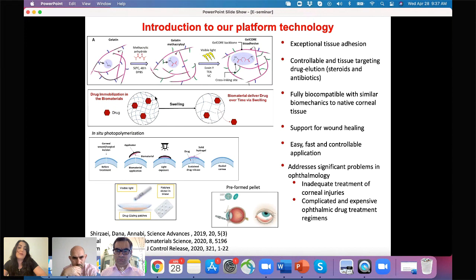And once we form these nanoparticles, they can be combined with the bioadhesive pre-polymer solution. And then the solution can be applied on the defect site on the cornea by using an applicator. We can use a contact lens as an applicator. Once we place the contact lens on the surface of the eye, we photopolymerize the hydrogel, and after that, the contact lens can be removed, and then we will have an adhesive layer of the hydrogel containing drug.